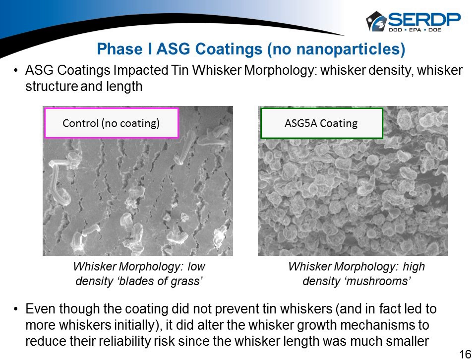And so this was our big aha moment, that our coatings, while they couldn't shut down whisker initiation, they clearly could change the behavior. So if I can make them short and they grow lots of them and then stop growing, that was more of a win-win than just completely shutting down whiskers, which in 2020 hindsight, you're not going to change an elemental characteristic.